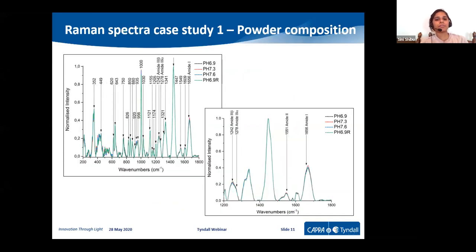And this is one of the papers we are going to publish soon in collaboration with UCC. According to their studies, they did some chemical method, some acidity changes in the milk proteins. So you can see there are different pH levels for the milk proteins: pH 6.9, 7.3, 7.6. And the last sample is pH 6.9R, that means restored milk proteins. At the beginning it had pH about 7.6. Then they added some NaOH and chemical reactions, and after that they came to 6.9.